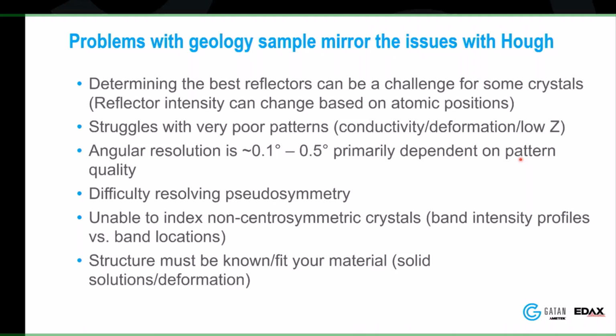bit different. Now, one of the things I've glossed over here, and I think is important to understand, is that the Hough basically reduces the entire pattern to a series of points, which are kind of lines. Spherical indexing in the dictionary approach is using every bit of information in the pattern. So we're not losing any information here. Intensity changes, very minor changes in the band positions, all that is taken into account. So even small things in the end really matter.